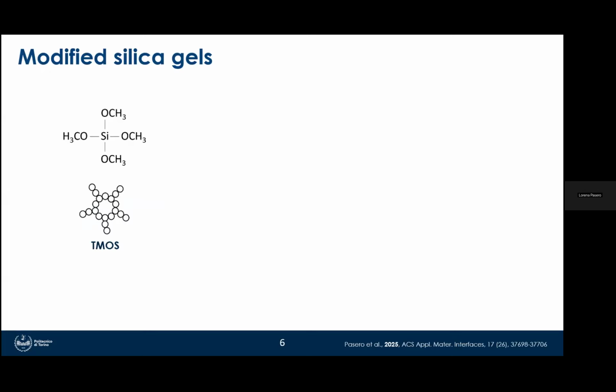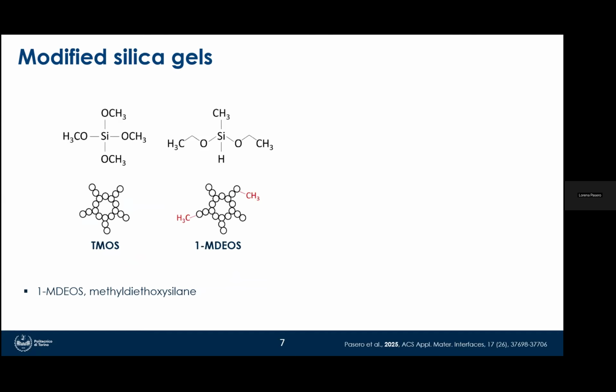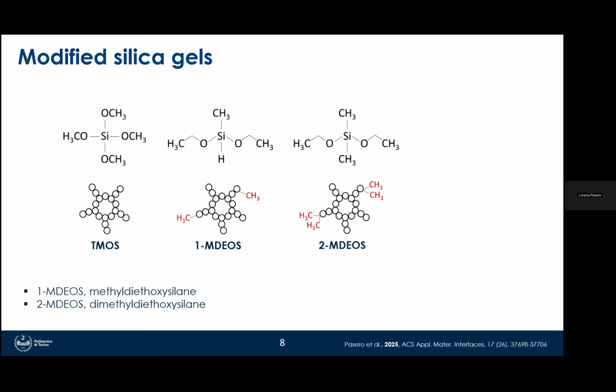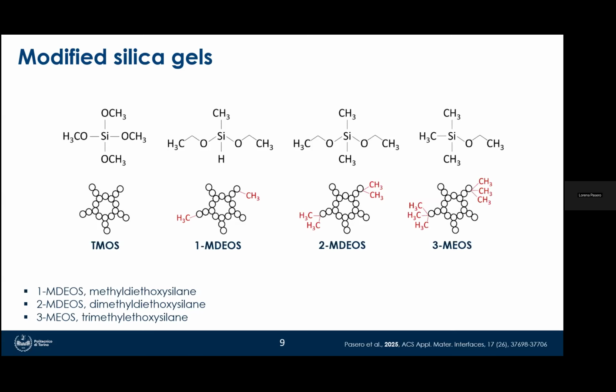And so what we did as the core idea of this study was to modify these gels, which in the traditional way are only formed of TMOS, by including into the gels some additives which are methylated silanes, the so-called methyl diethoxysilane with 1 methyl group, then dimethyl diethoxysilane with 2 methyl groups, and trimethyl ethoxysilane with 3 methyl groups. So by progressively introducing these methyl groups, we aim to replace silanol groups with methyl ones and to increase the hydrophobicity of the gel, to modify the network structure and also to reduce the protein adsorption. And the idea was to make the gel more hydrophobic, but also to tune and assess the surface chemistry, cross-linking, and elasticity, so the gel properties.